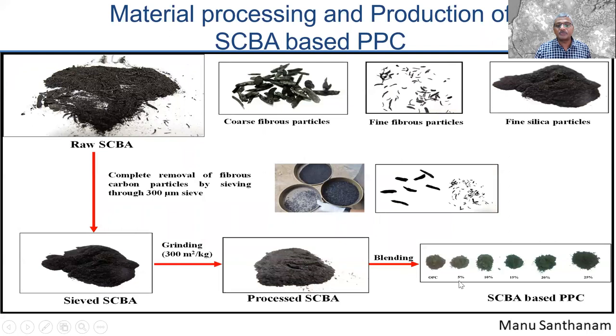We made blends with 5%, 10%, 15%, 20%, and 25% replacement of cement with bagasse ash. The reason, obviously, is that at 5% you can still use it as a performance improver. At 25%, you can think about utilization as a Portland pozzolan cement. The intermediate values were just to understand what happens as we keep on changing the content of bagasse ash as a replacement of cement.